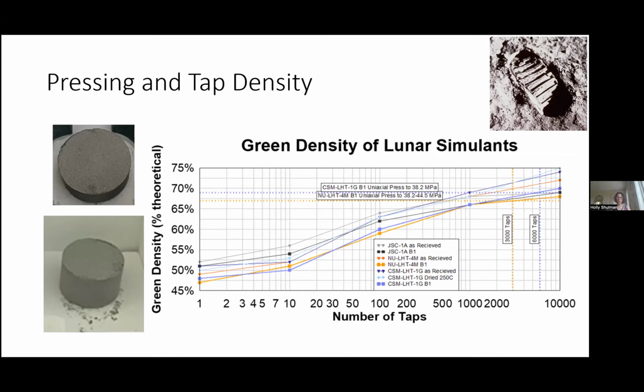And so what's interesting is we use something called tap density, where you put this in a cylinder, measure its mass and its volume, and one tap is really what we would call the bulk density. And the bulk density of this material is pretty high, but it's because it has a very large particle size distribution, the more coarse particles kind of touch up against each other. And then as you tap it, just mechanically, the finer fractions will fit into the interstices. And so then you develop a higher and higher density with more taps, even to the point where if you pressed it uniaxially with reasonable pressure, you're able to just tap it to that density.